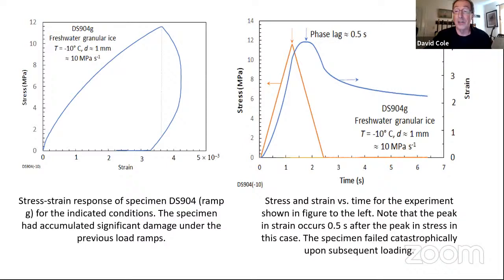Another case, this is faster, 10 MPa per second, a little over a second to get to our almost 12 MPa. In this case, a half a second phase lag between the peak stress and the resulting peak strain. This is just huge. I'll get back to this in a second, but this line I've drawn, basically the area under the curve here is the strain energy that is being released after the peak stress. So once the stress starts dropping, the area here represents the strain energy that's being dumped back out of the sample.